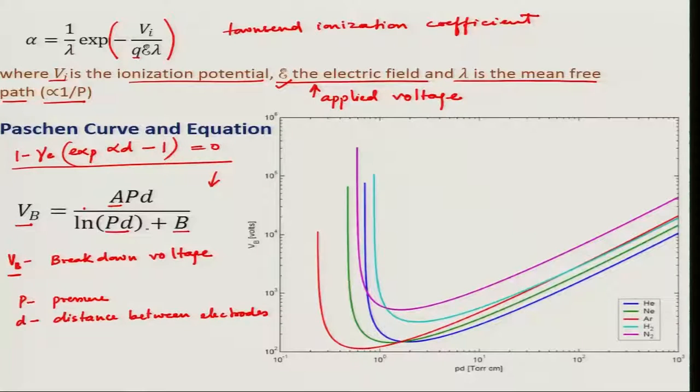Now this equation is known as Paschen equation, and the curves which are shown in this graph are called Paschen curves, and these are shown for different gases. How the breakdown voltage changes with the product of p and d, pressure and the distance, okay. So if you see these curves, for a fixed separation between anode and cathode, at low pressures you need very high voltage, okay, and also at very high pressures you need very high voltage, okay. Now we can explain this phenomenon like this. In the low pressure regime, when the pressure is low, there are fewer gas atoms to be ionized,